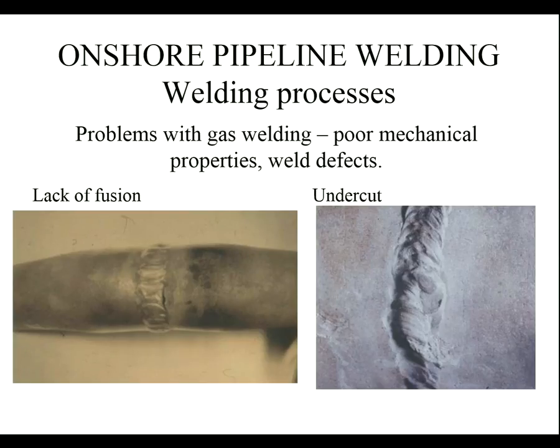And the other one is undercut. So here's a good weld. And then this welder had a wobbly. And the weld, instead of doing what you normally do, there's a manipulation of the weld, sort of like this, going down there. And then the welder's gone. Probably because they're bored. And what's happened is all the weld metal's been deposited on this side, and we get an undercut here. So this part of the weld is not filled up. And then the weld tends to improve a bit afterwards. I saw one welder yawn and got a lovely undercut from that, so you can tell exactly what happens there.